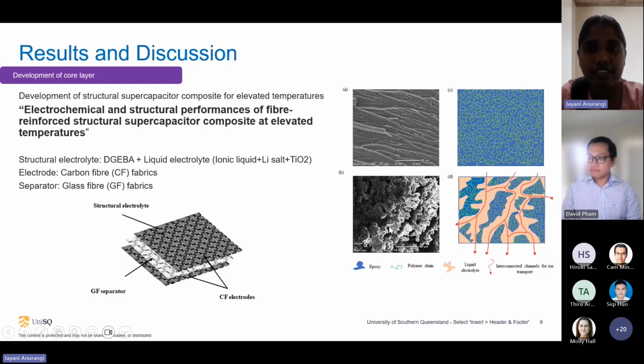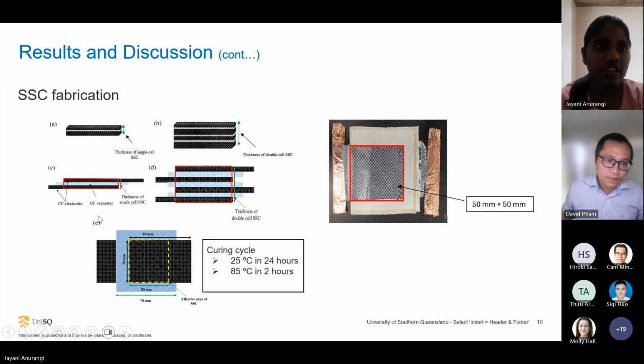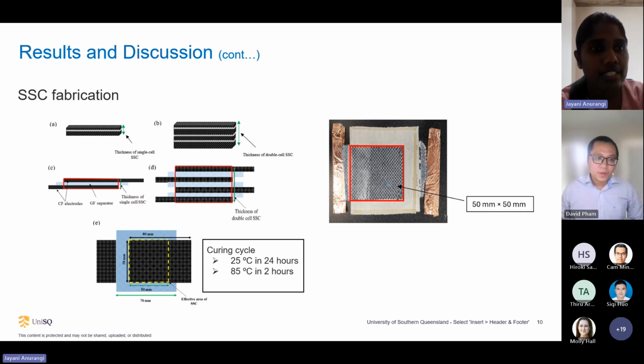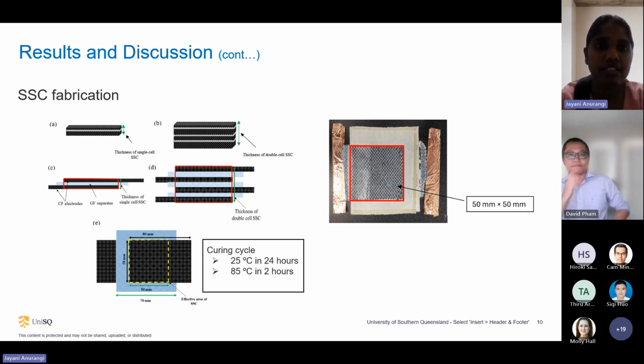Therefore, it has the ionic conductivity in the developed structural electrolyte. In this supercapacitor, I use carbon fiber fabrics as the electrode and glass fiber fabric as the separator. In fabricating the structural supercapacitor, I developed both single and double cell structural supercapacitors as shown in this figure.